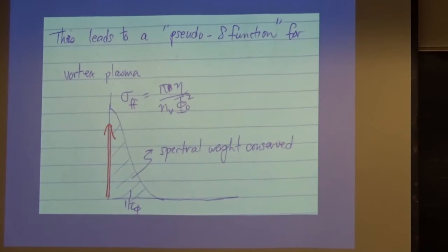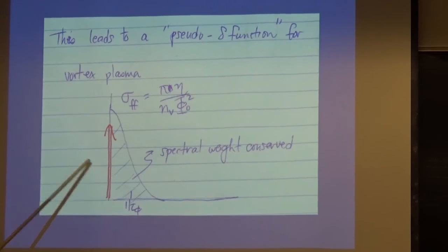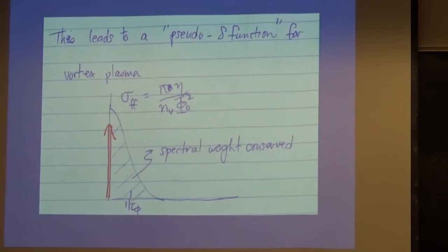So the key result here is that if I started off with a superconducting state in which I have a delta function in my optical conductivity that stands for the infinite conductivity of the superconductor, if I now have a gas of free vortices, equal amounts, it doesn't have to be equal, but without an applied magnetic field, I'll have equal positive and negative vortices, the delta function is not going to be a delta function anymore. It's going to broaden, and I'm going to call that a pseudo-delta function because it's different than the Drude conductivity you spoke about earlier. It's a remnant. It's coming about from the superfluid density. It has a spectral weight directly related to the phase difference that I spoke about earlier, except now it acquires a width. And what I want to consider now is,